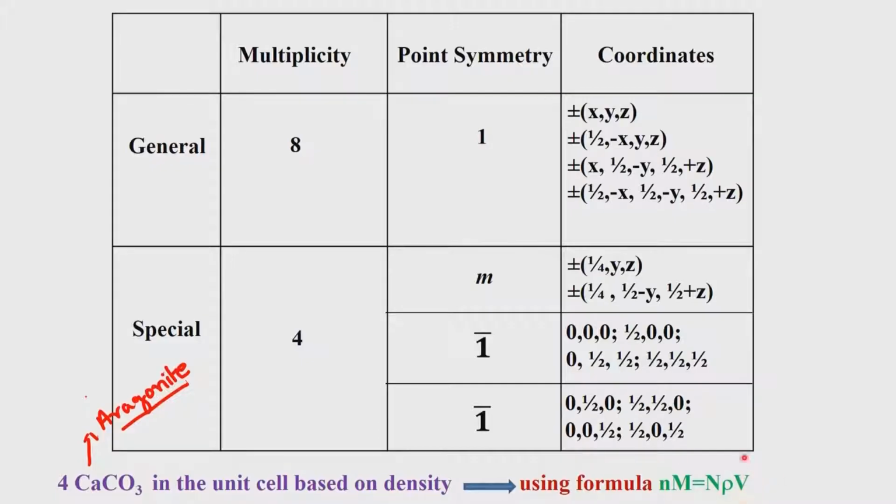So, we have volume known in this expression, we know the volume, we know the Avogadro number, we know the molecular weight. The two unknowns are the number of molecules in the unit cell and the density associated with the crystal. The density associated with the crystal can be measured. In earlier days, as I mentioned in the previous class, we were asked to determine the density whenever we do any crystal structure determination. It was a compulsory requirement, but now people do not bother about it and they simply get whatever density the software gives, they assume that is the density of the crystal.